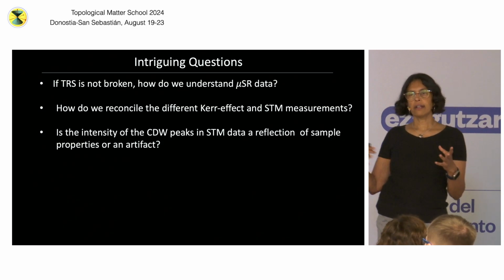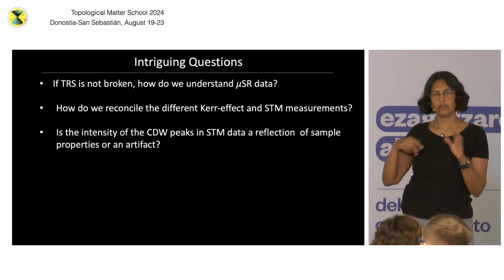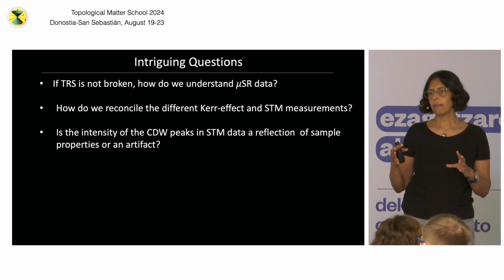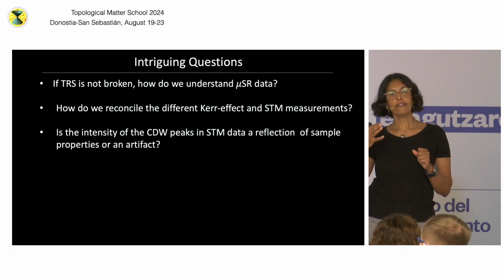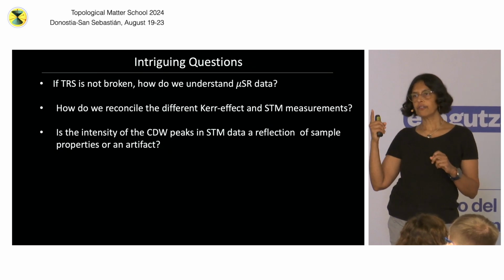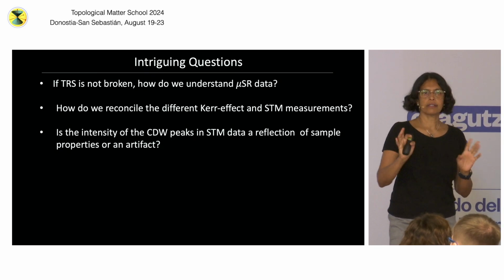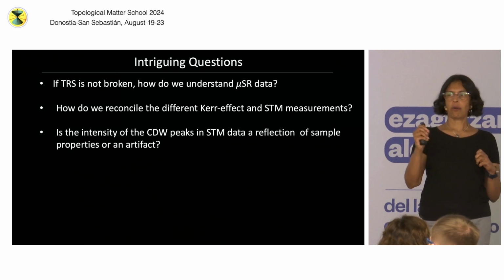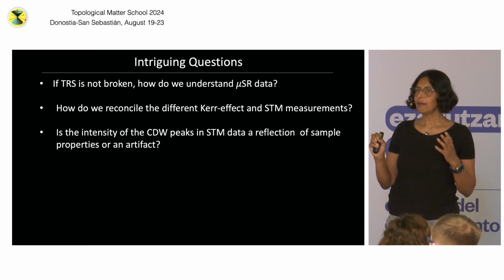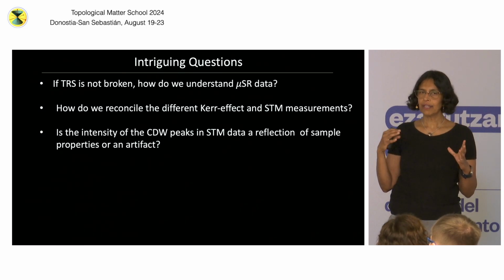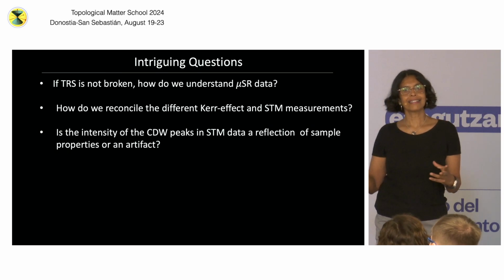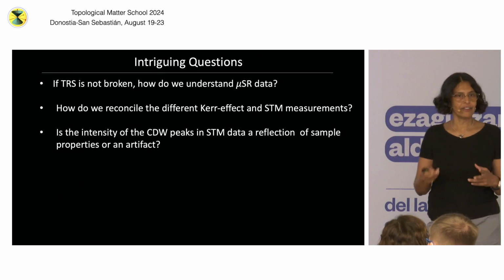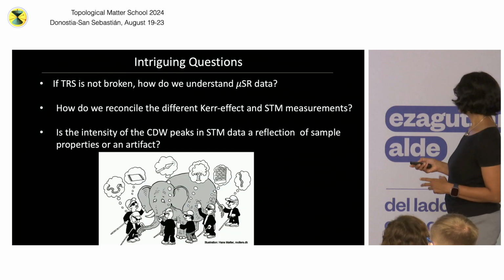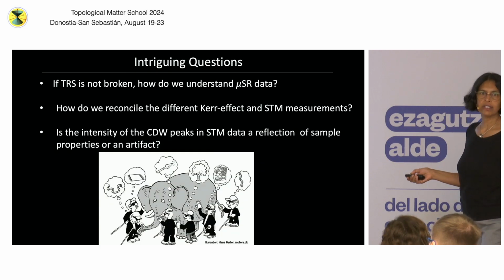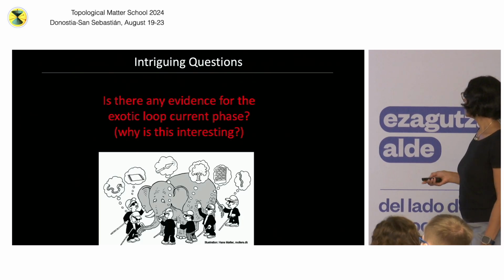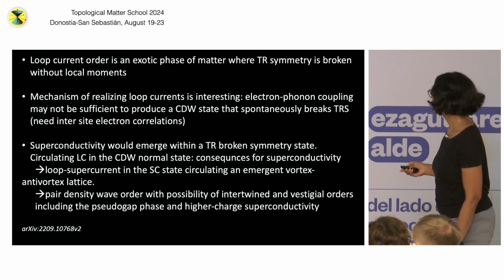If you take a material and any random system and you scan it and look, you see atoms, and then you take a Fourier transform, depending upon the tip that you have, the heights of the Bragg peaks, not the CDW, the Bragg peaks in a Fourier transform in STM data can be very different from one another. And that's something to do with the tip. So when that's the case, how do you take the STM height seriously, okay? So these are the questions, and this is where we were when we first started this experiment. You know what this means. Lots of different groups saying lots of different things.